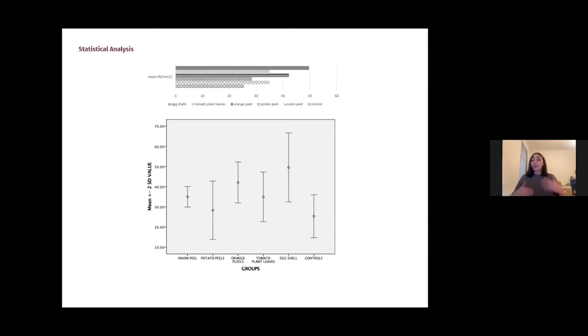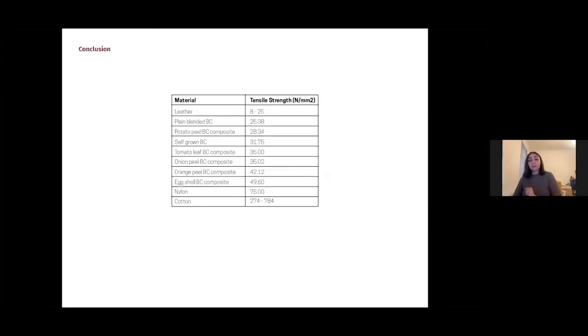And then for even more detailed information about these materials, a post hoc LSD test was also performed with a sensitivity threshold of 5% in order to compare between the groups and figure out the significant difference between them. And it was found that between the control group and all the other groups, there was a significant difference, except for the potato peel group, which was very interesting in my opinion.